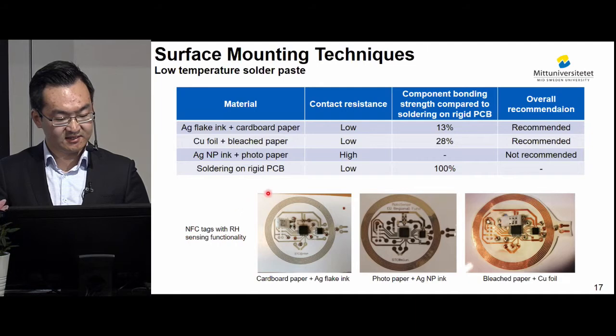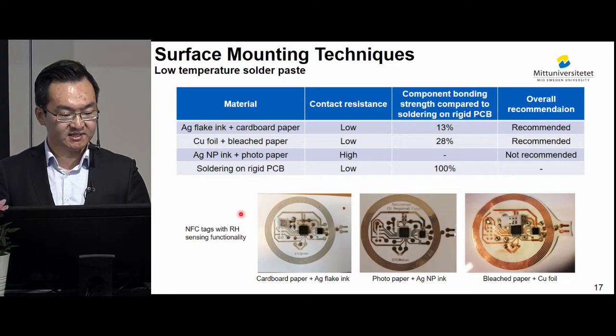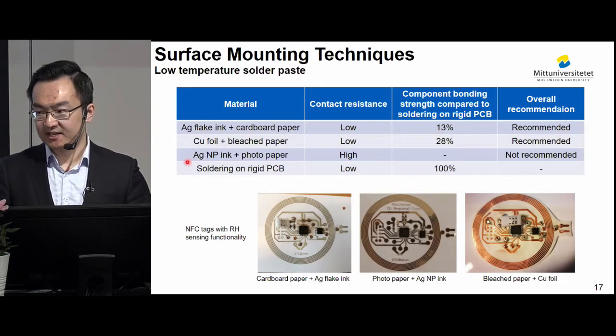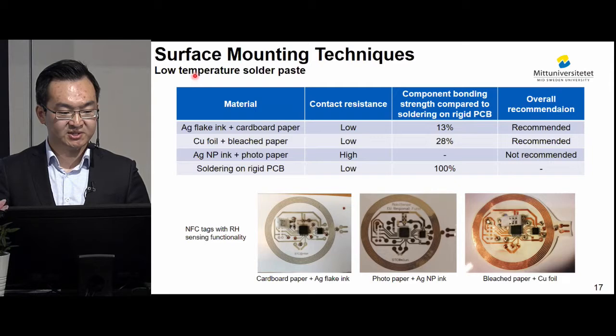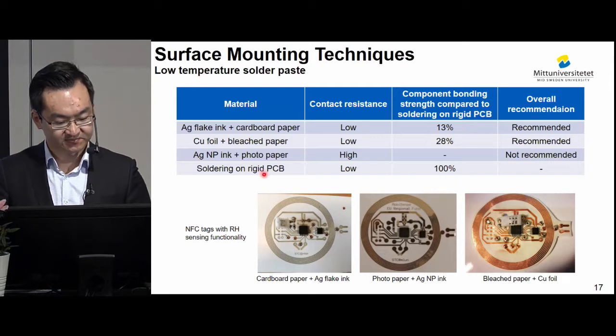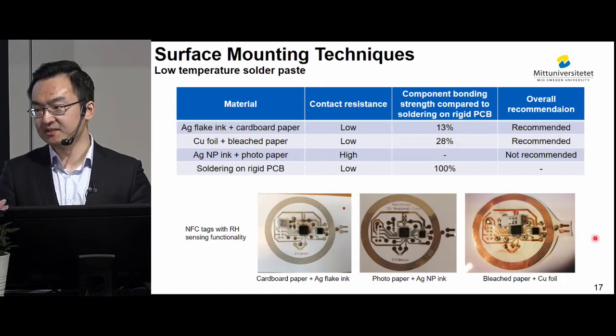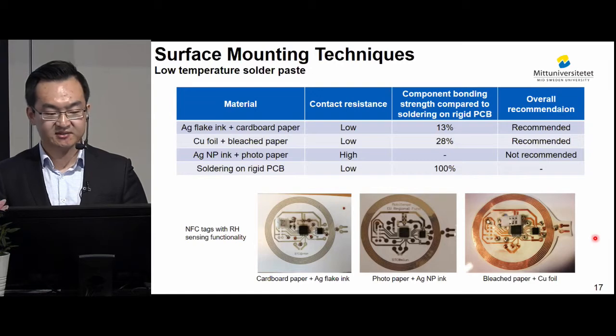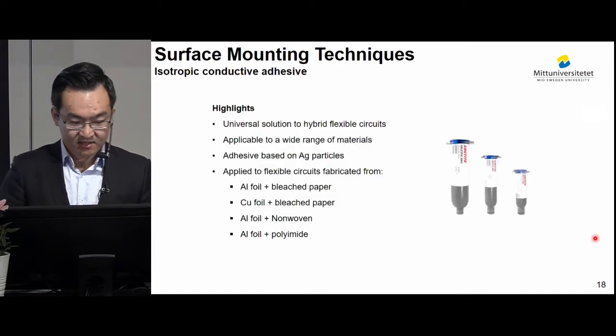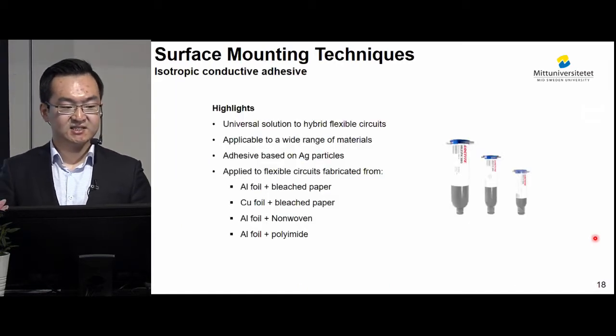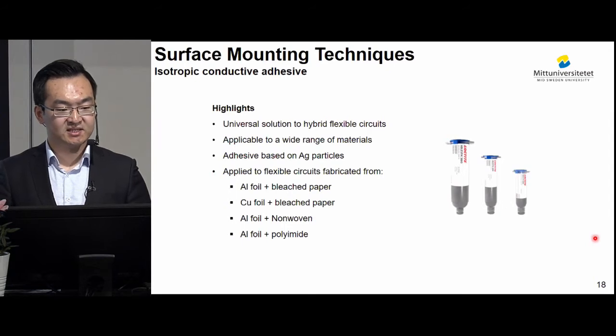And here we show 3 NFC tags that are fabricated using these materials and using this low temperature solder paste technique, of which the first and the third tags can communicate with NFC readers successfully. The second surface mounting technique is to use an isotropic conductive adhesive.